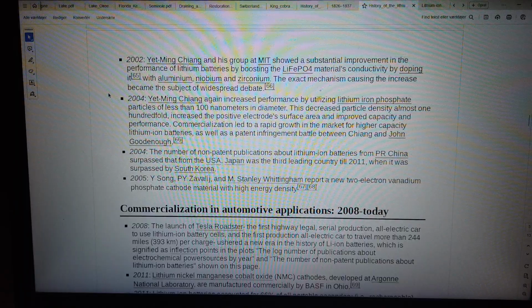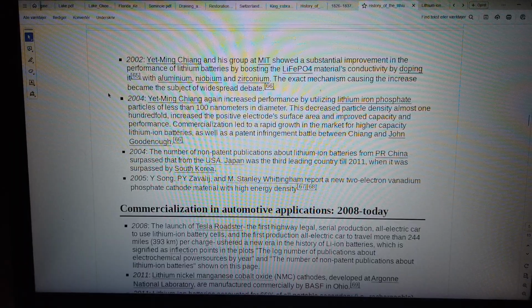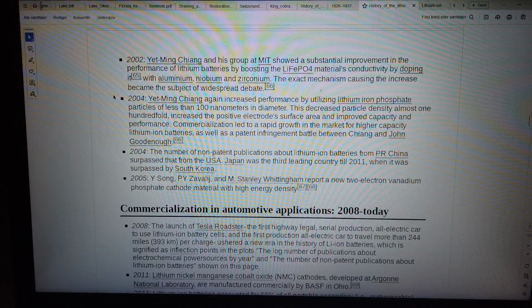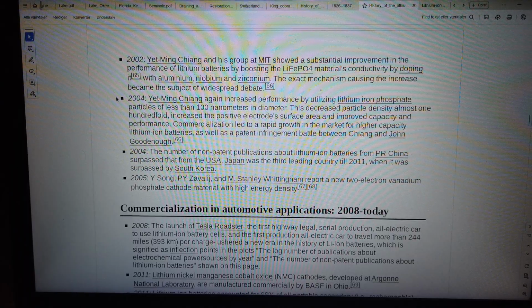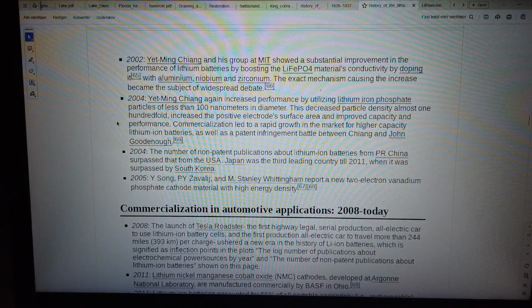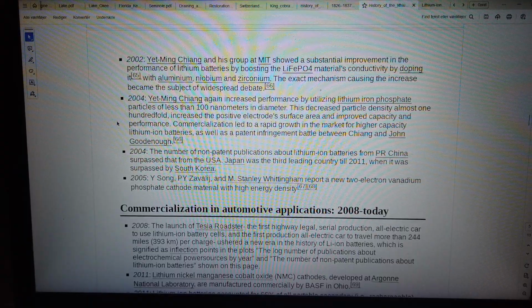2004, Yet-Ming Chiang again increased performance by utilizing lithium iron phosphate particles of less than 100 nanometers in diameter. This decreased particle density almost 100-fold, increased the positive electrode's surface area and improved capacity and performance. Commercialization led to a rapid growth in the market for higher capacity lithium-ion batteries, as well as a patent infringement battle between Chiang and John Goodenough. 66.